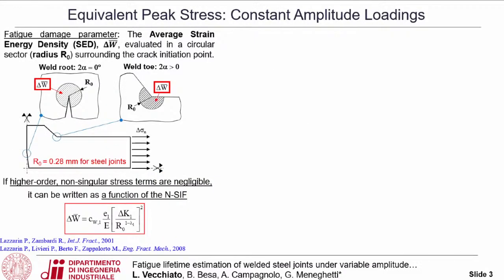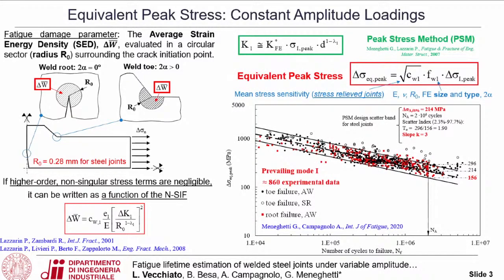Adopting as a fatigue damage parameter the strain energy density averaged over a circular sector of radius R0 at the V-notch tip, as proposed by Professor Lazzarin almost 20 years ago, it has been shown that in the case of negligible higher order and non-singular stress terms, the SED can be written as a function of the NSIFs. And by combining the strain energy density approach with the peak stress method, it has been shown to be possible to define an equivalent peak stress as a fatigue damage parameter. In particular, a fatigue design curve for prevailing mode 1 has been proposed in the literature and in the reported paper. And it's the one reported in this slide.